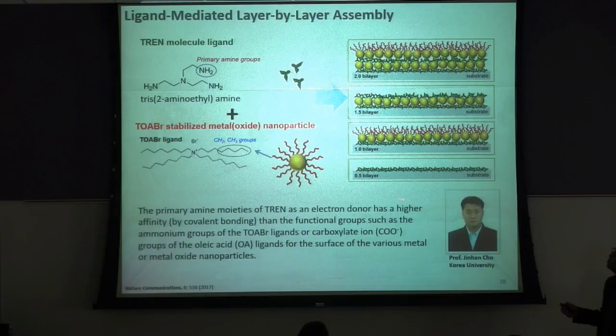So we can move again to the TOABr molecule solution. Now the TOABr can replace the remaining bulky ligand and adsorb on the surface of the gold nanoparticle layer. Then we move again to the nanoparticle solution. Basically, by repeating this layer by layer process, we can create a conformal and very thin coating of the nanoparticle layer on any kind of substrate.